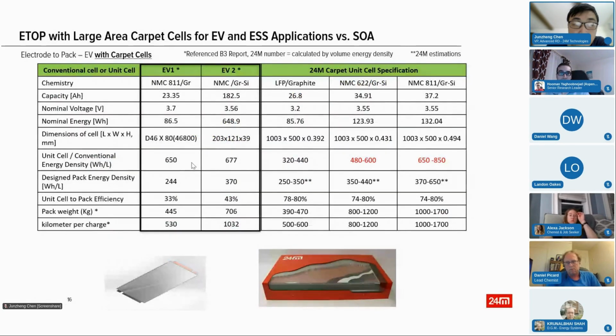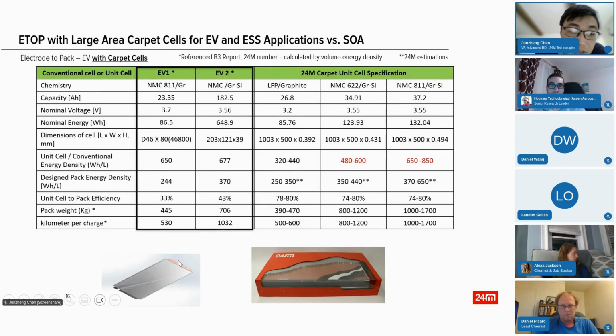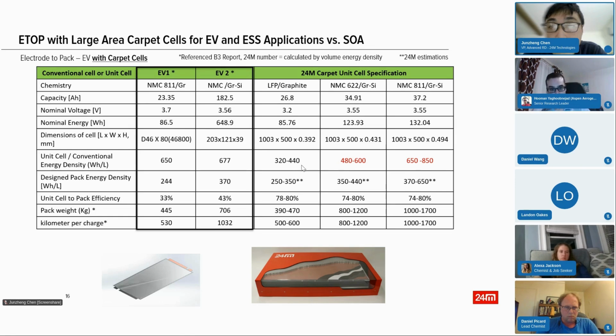So with this concept and integration with a large format unit cell, we demonstrate a unit cell specification of the electrode, LFP, ranging from 320 to 440 watt-hour per liter. And then with 78 to 80% LFP pack efficiency, we can easily achieve 250 to 350 watt-hour per liter. Then we can use the LFP graphite cells to compete with the NMC graphite cells, with very low cost and relaxed safety and cooling needs. And if we integrate it into the NMC system, we can easily achieve more than 350 to 650 watt-hour per liter pack level demonstration. Then in this case, the kilometer per charge can be very, very high.